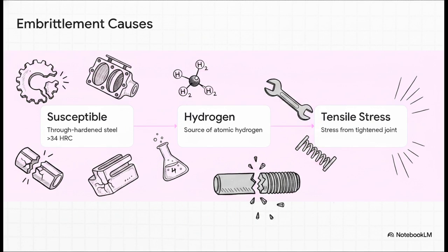It is a catastrophic, delayed fracture phenomenon where high-strength bolts can just snap in half days or even weeks after it's been assembled. No warning. For this to happen, 3 exact thermodynamic conditions have to perfectly align. First, you need a hard, susceptible material, usually over 34 Rockwell C. Second, you need a source of atomic hydrogen, which is actually often introduced during the acid cleaning or electroplating processes we talked about earlier. And third, you need sustained tensile stress from the tightened joint.